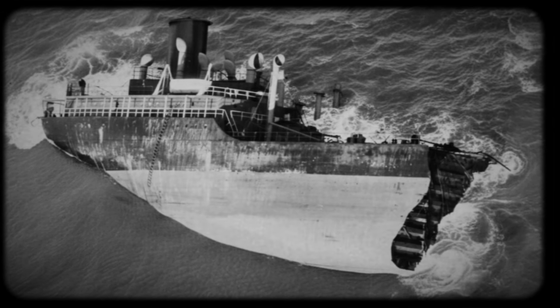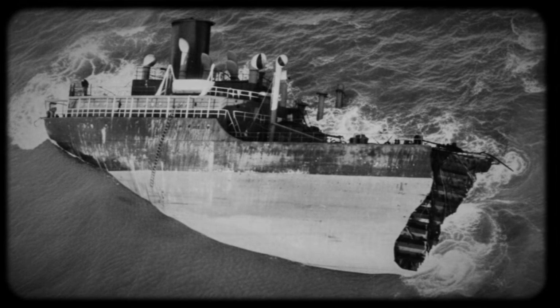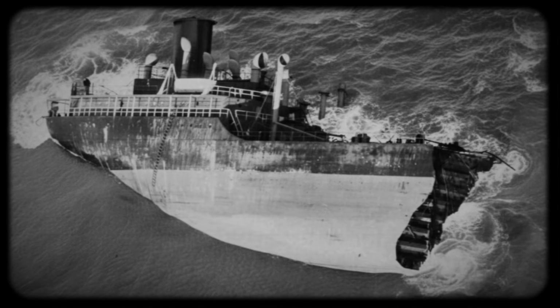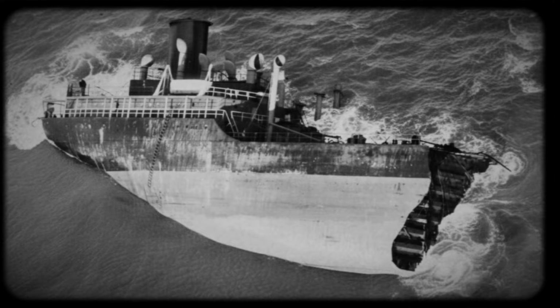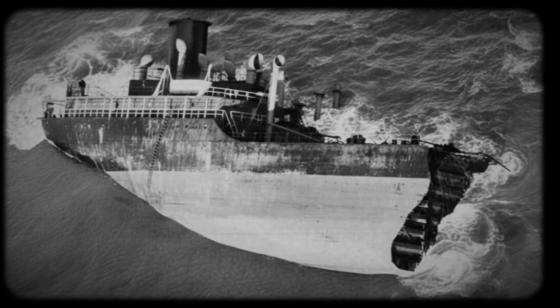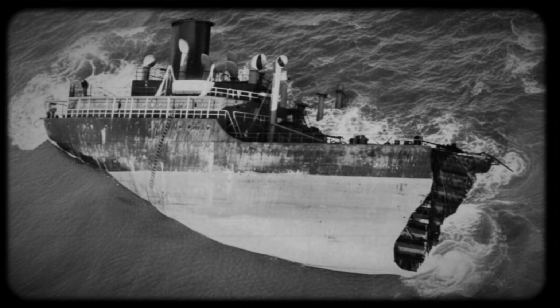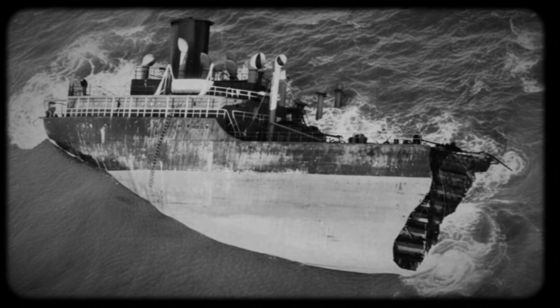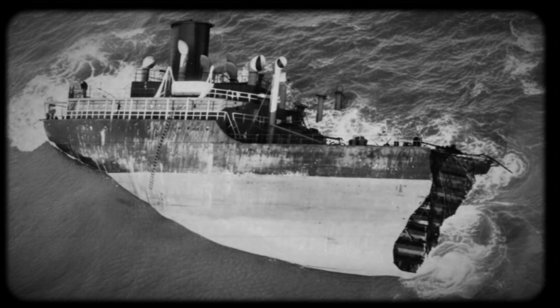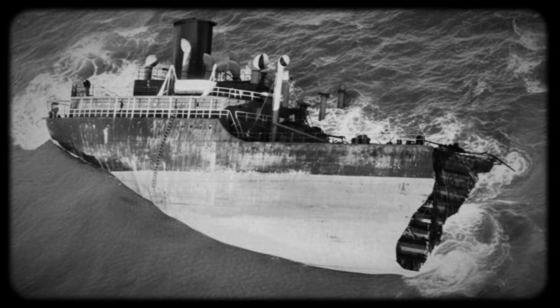Tipper realized these factors created a perfect storm for catastrophic failure. Start with steel whose ductility drops in cold water. Add residual stresses from poor welding sequences. Concentrate those stresses at square corners and abrupt transitions. Then put the ship to sea in the North Atlantic during winter. The result was predictable: brittle fracture.